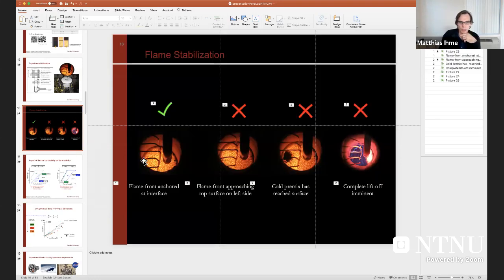Yeah, that's a really good question. What we have not seen is hotspots, but because of the cyclic heating and cooling, we're seeing quite some thermal expansion. But maybe I just go to one picture here to illustrate the idea. The porous media burner is certainly a very homogeneous system, and because of this internal dispersion, we're getting a very homogeneous mixing system. So it prevents the occurrence of hotspots under stable conditions. We haven't encountered this. The key challenge is that because of these very strong temperature gradients, you get quite a bit of thermal expansion, and this is really causing material stresses on this system.